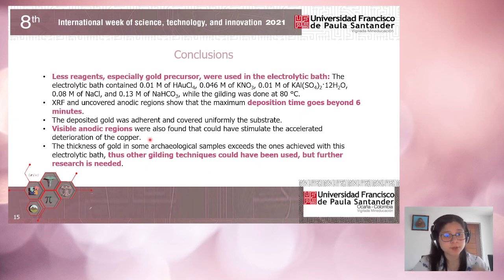Also, we found visible anodic regions that could have stimulated the accelerated deterioration of the copper, taking into consideration all the environmental humidity and salt concentration, and also the corrosion agents found in burial sites. The thickness of gold in some archaeological samples exceeds the one achieved with this electrolytic bath, if we compare the 0.5 to 2 micrometers reported by Lechtman with the about 10 micrometers at Dos Cabezas.